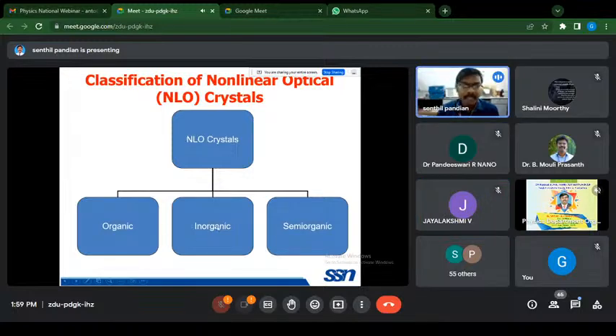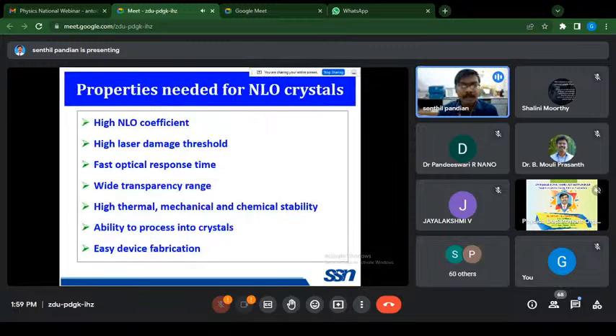We cannot grow very highly efficient material in the inorganic category, but in order to get the advantages of organic and inorganic, people are now trying to grow crystals as semiorganic single crystals. Here, in the semiorganic category, one can achieve large solution-grown crystals, and the SHG efficiency of these crystals is very high compared to other solution-grown crystals. These are some of the properties needed for nonlinear optical single crystals.